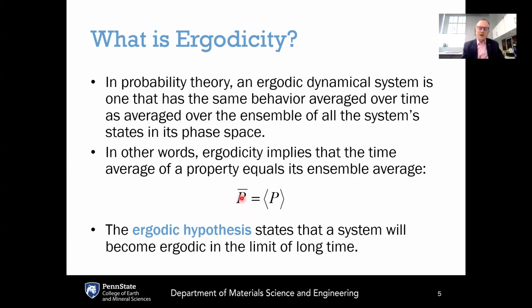And if this time average is equal to the ensemble average, then the system is ergodic, at least with respect to that property. If these two values are different, for example, maybe you have a system that is evolving over time, so that if you measure the density over time, there's going to be some systematic evolution of the density, such that the time average is different from the ensemble average. If that's the case, then ergodicity is not satisfied, and so the system would be non-ergodic.